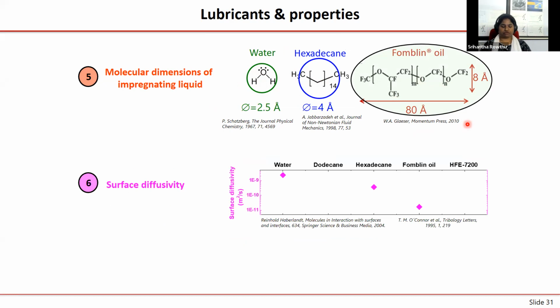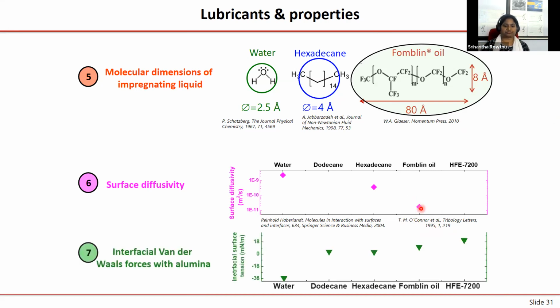So then looking at surface diffusivity. What if, after several cycles, some of the oil has been rubbed away from the main contact area? Then the oil should be able to come back to that area between these two solids. For that, it's actually a surface diffusion process. It's like molecular walking. So the surface diffusion process has to be very high. But then unfortunately, because it has a higher viscosity, here it is sort of a trade-off. Surface diffusion is not very good for the Fomblin oil. And then you also want that particular oil to be bonded to my substrate very nicely.